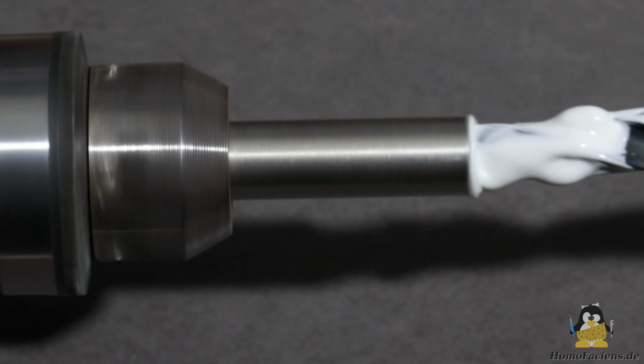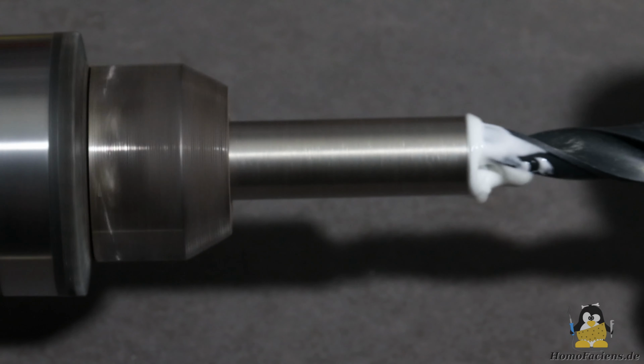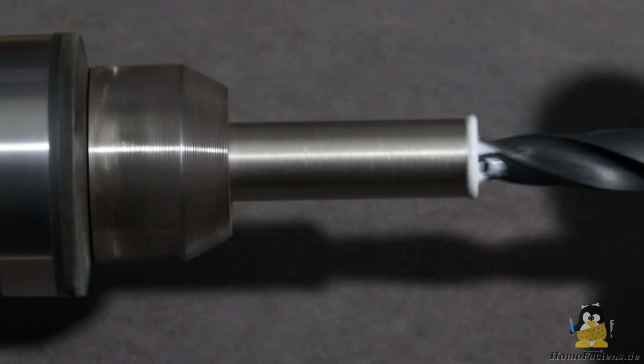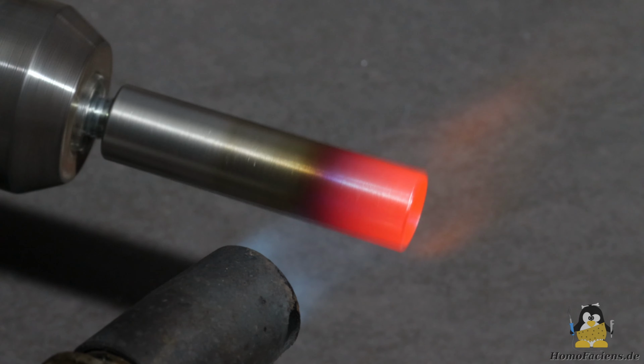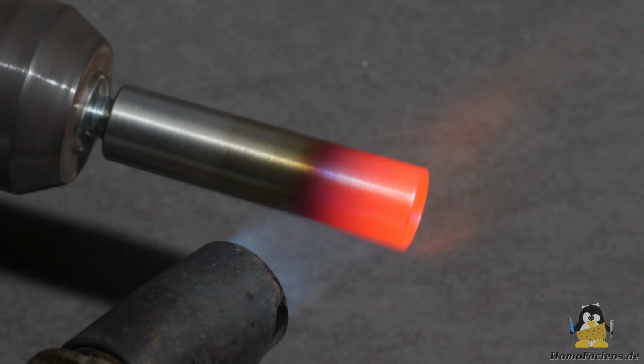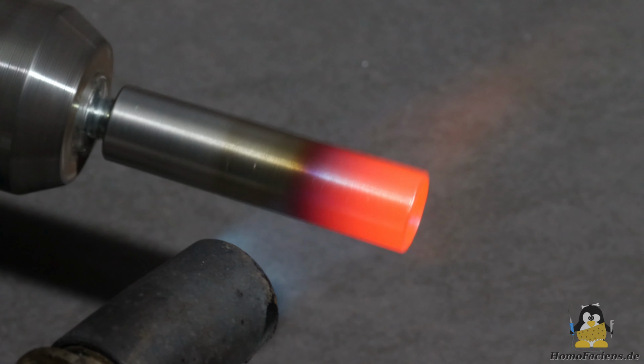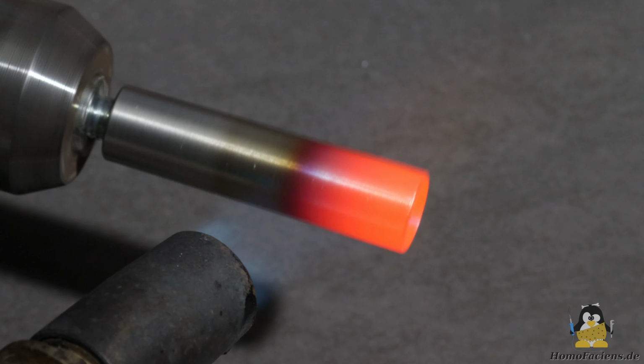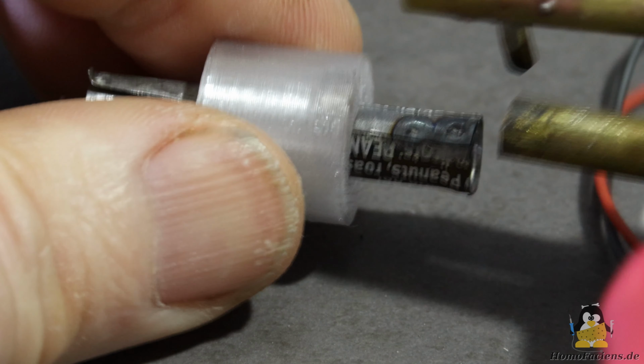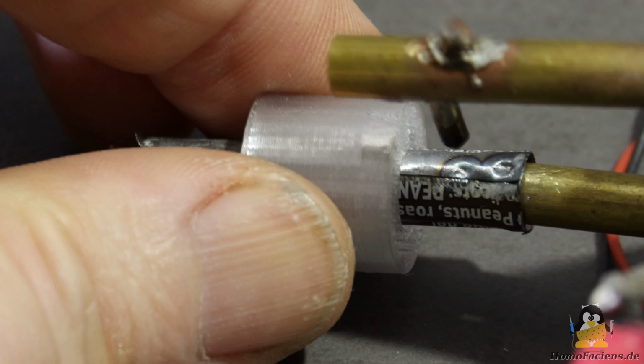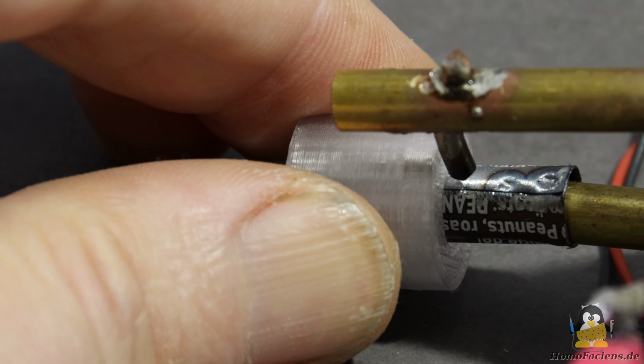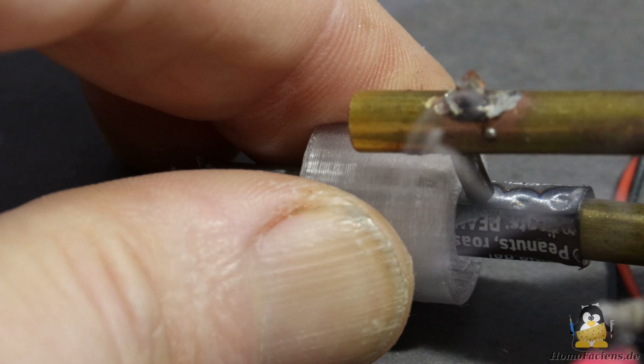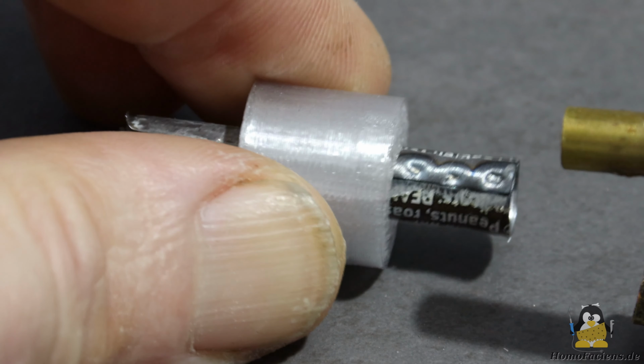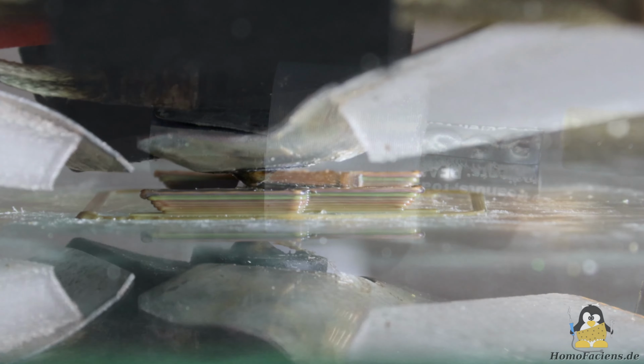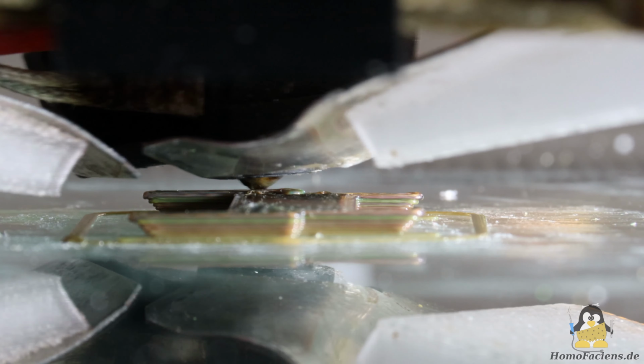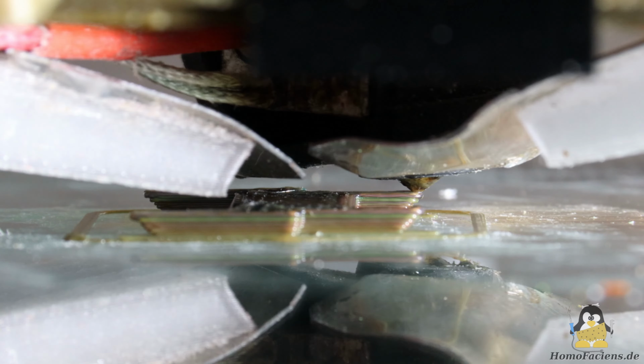Approach 1 was polishing the inside with abrasives of different grain sizes. Approach 2 involved coating the inner wall with enamel. And finally, approach 3 was to make insets from smooth steel sheets. All three approaches led to more or less the same results.